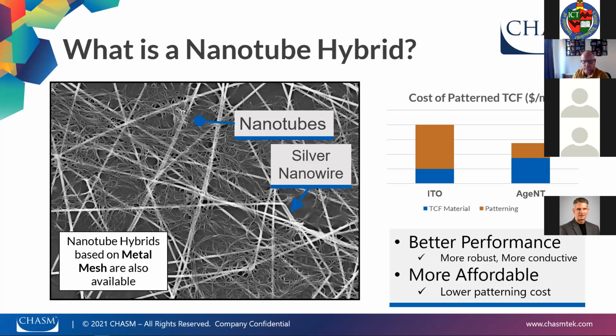Looking at the image on the screen, for traditional silver nanowire films, anywhere where you don't see the silver rods is non-conductive. So in this case, the silver rods that you see are conductive silver, and in between those, the spaghetti-looking material is actually carbon nanotubes that have been printed in a light solution in order to be able to show the differences between those.